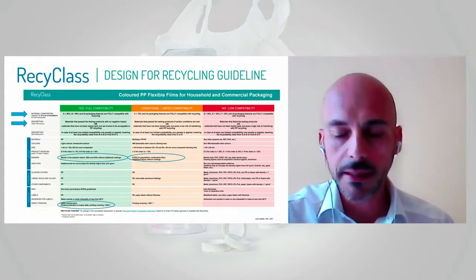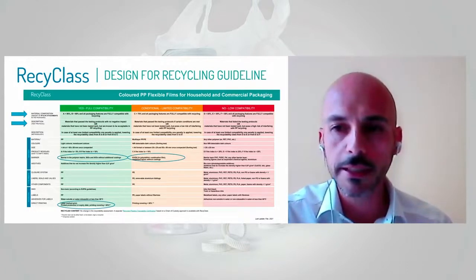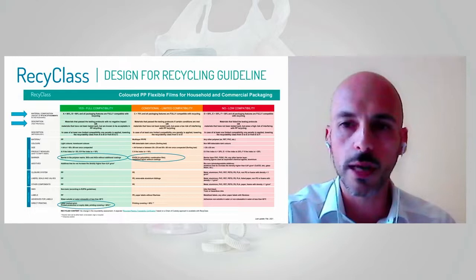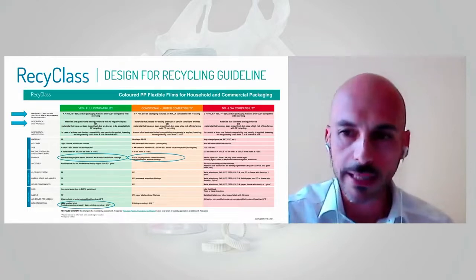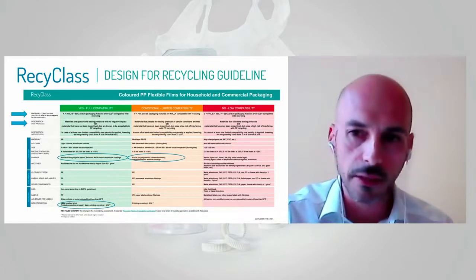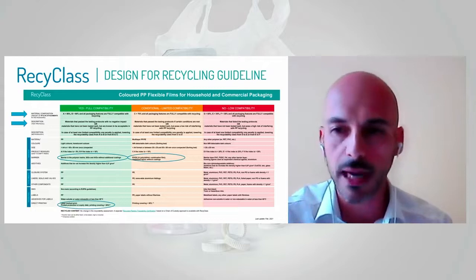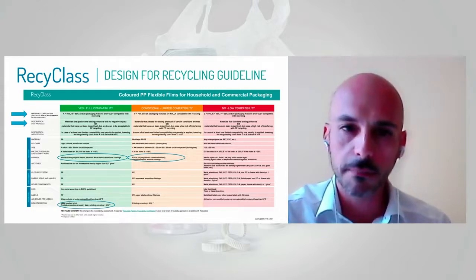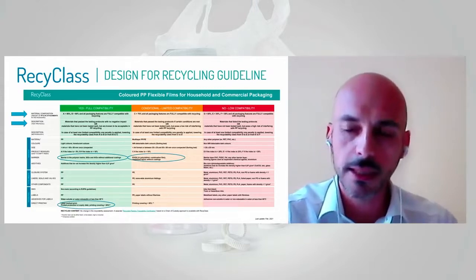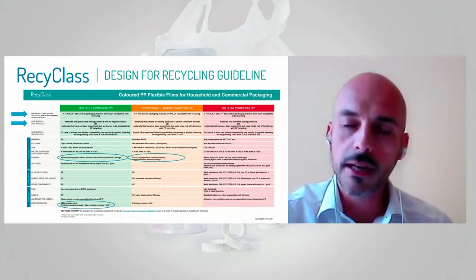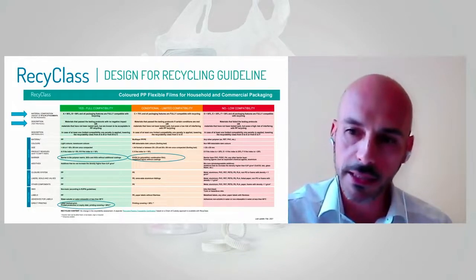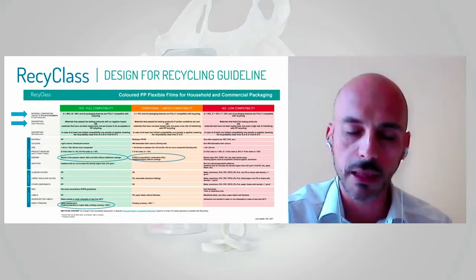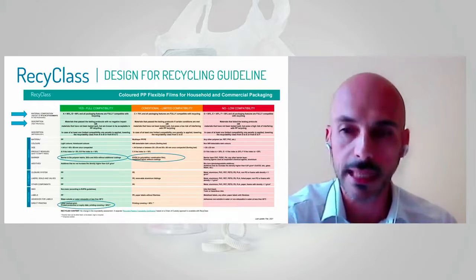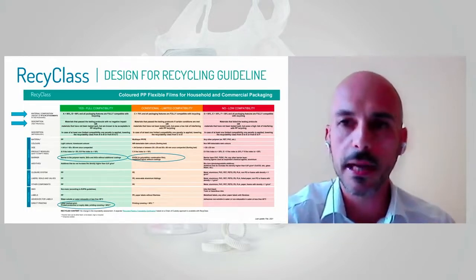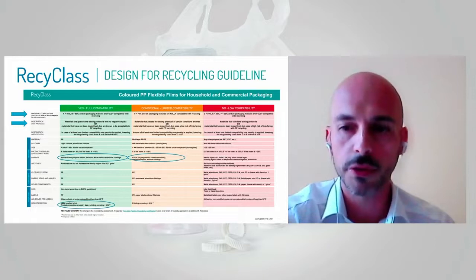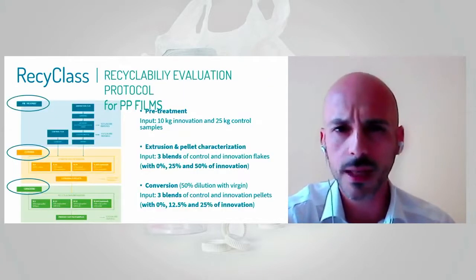And talking about printing inks, we have ongoing test campaigns for inks where we have already identified and confirmed that nitrocellulose binders as well as PVC binders should be avoided because they are not thermostable at all. And the overall goal in terms of pigments and binders, in particular talking about inks, should be to prefer polyurethane, which is the most thermostable we have today on the market.